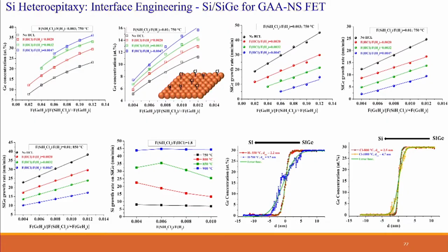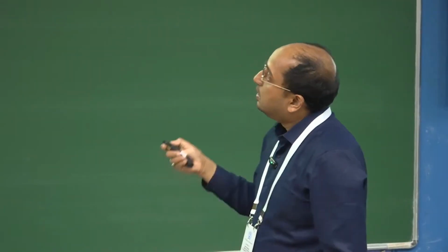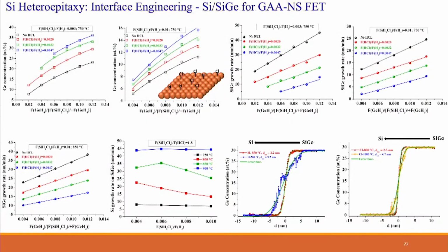So what happens? Atoms need free, open sites to incorporate and nucleate. When the majority of these sites are occupied by chlorine, which doesn't want to dissolve, the growth of a monolayer takes that much longer. Which is why, with increasing HCl concentration, the growth rate simply falls.